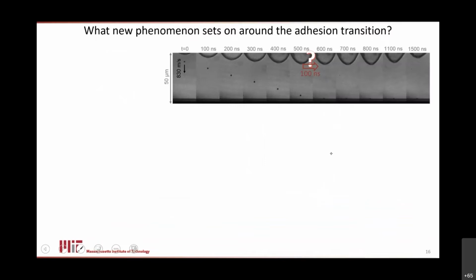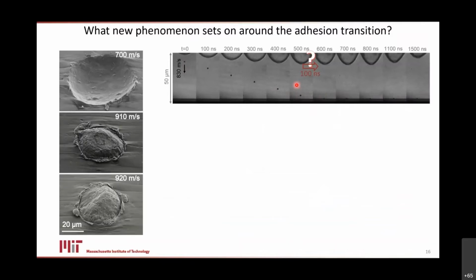Well, actually, this is one of the very first things we tried to work on 3 or 4 years ago when we were getting started, because we noticed that we would take data like this. Here's an aluminum particle. It flies in, it strikes the substrate, and it sticks. Well, we have no idea what's going on right here where it's impacting and touching down. And that touchdown event is critical because something's happening at that touchdown that separates a bouncing impact from a sticking impact like the one shown here.